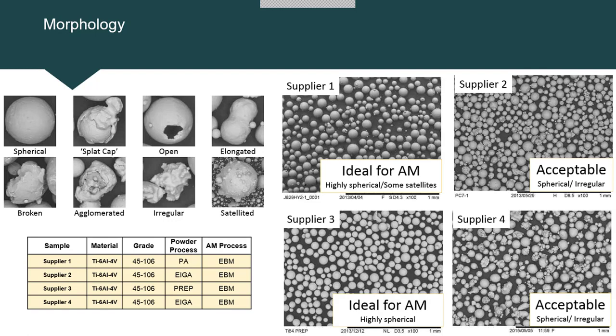Another issue is satellite. So fine particles will again impede flow, but also they become a health and safety risk. So some of the satellites you see can be much, much finer than the bulk. So typically speaking, you can get sort of 5 to 10 microns, and they then start to pose safety risks.